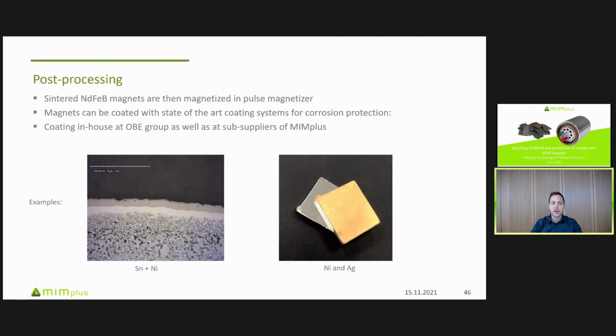After the sintering step, you take the parts out of the furnace and they are non-magnetic. Then you can post-process them, for example, with machining if you need. But the advantage of MIM is that you don't need that, because we have a high complexity. The magnets can then be directly pulse magnetized to make them permanent magnets, or they can be coated with several state-of-the-art coating systems that are also state-of-the-art for sintered magnets that have been on the market for several years. Typical coatings are, for example, nickel-copper-nickel, or also tin-nickel, or nickel-copper-nickel and gold, which we developed in-house at the OBE Group. And we also have several sub-suppliers with which we work together to coat our recycled and virgin MIM magnets.